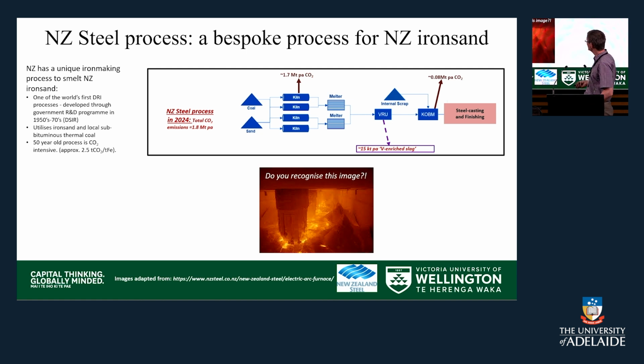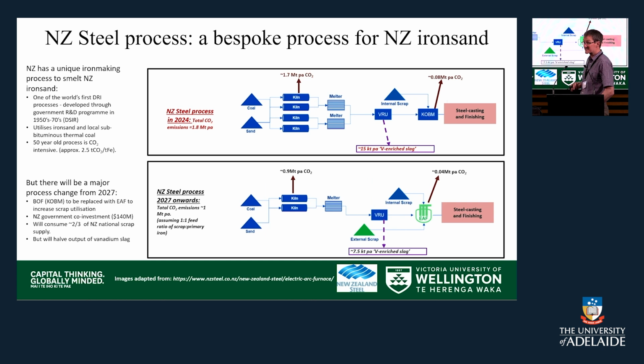And that's relevant too, because what New Zealand Steel and BlueScope are about to do is they're about to put in an electric arc furnace into this system so that they can increase the scrap utilisation, which is great from a CO2 perspective, but it means we're putting half as much iron sand in, which means it's putting half as much vanadium in, which is producing half as much vanadium-enriched slag. Vanadium is a critical metal. It would be ideal if we weren't doing that, but from a dollar's perspective, it doesn't make much sense to do anything else.